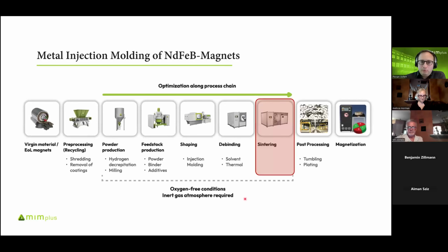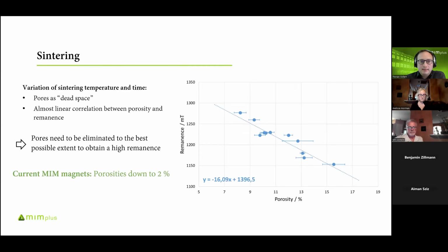Then we have removed our binder, and then it's possible to sinter our part to full density or nearly full density. This is basically the main challenge: to remove the whole porosity from our magnets, because this is also a crucial influencing factor on our magnetic properties, especially the remanence. These are also some experiments I did a few years ago. This is the correlation between the remanence and the porosity. You see an almost linear correlation because the pores act as empty space and do not contribute to the magnetic flux.